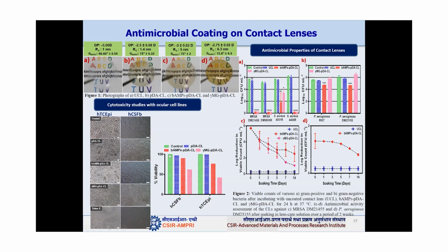You can see here that this is the control viability, and this is for the PDA coating. This is for the antimicrobial peptide. So they are quite safe, although we got some reduction in the cell number with gamma MG peptide. So we can say that the antimicrobial peptide coatings are quite safe. Then we did the antimicrobial analysis of these coated lenses, and we found that not only for gram positive but also for gram negative bacteria, there is a sharp reduction in the bacterial number when we put these coatings on the surface.